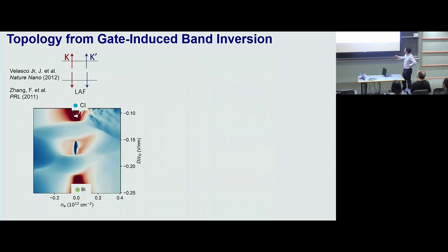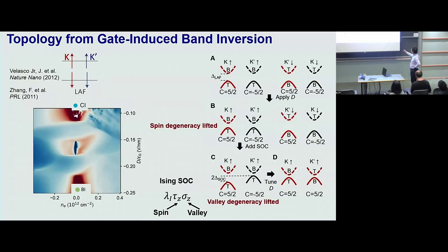And we think it may be the so-called layer antiferromagnetic state, in the sense that electron spin, no matter which valley it is in, has a layer preference. Okay, spin up is in the top layer, spin down is in the bottom layer. Neglect the 3 layers in the middle. They are not relevant for low energy physics. If you start with this state, you get a Chern number distribution like this. I mean, valley projected Chern number, okay?